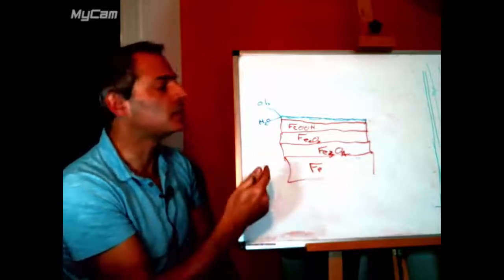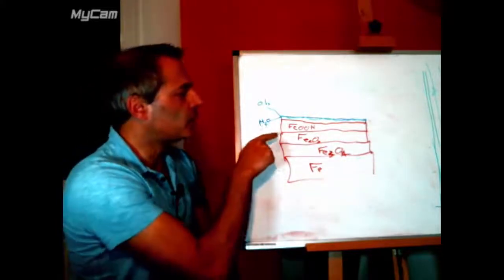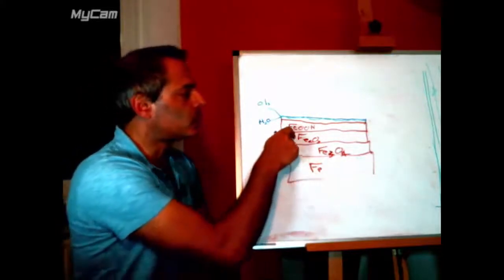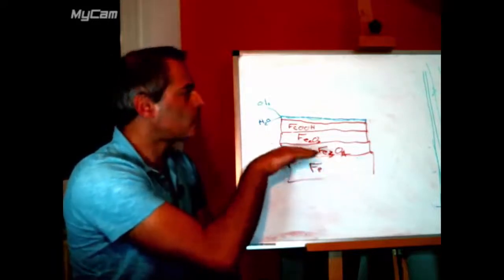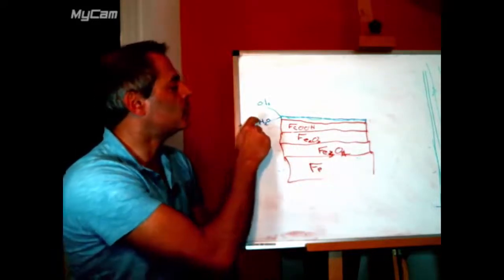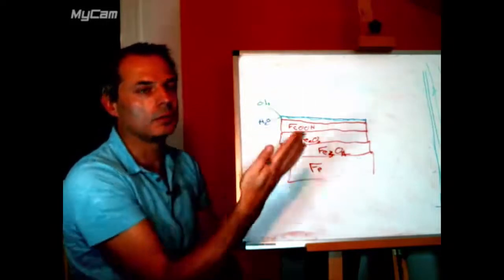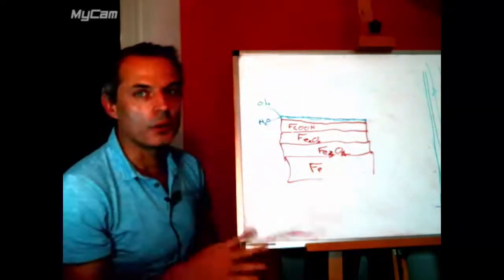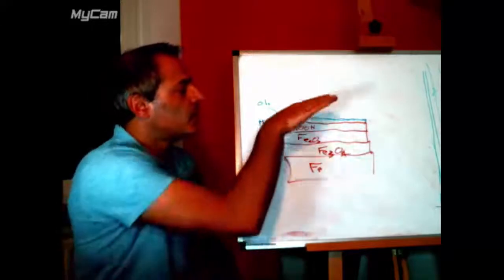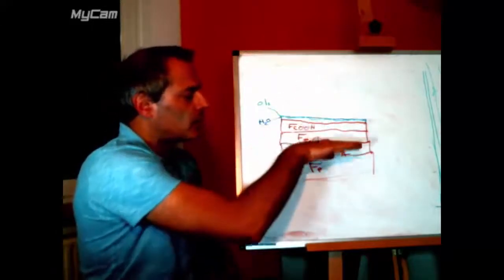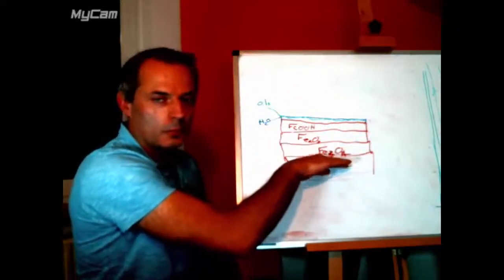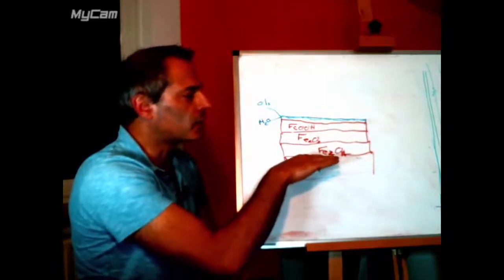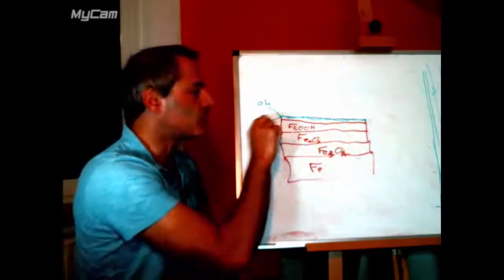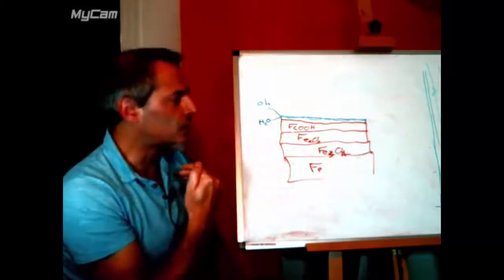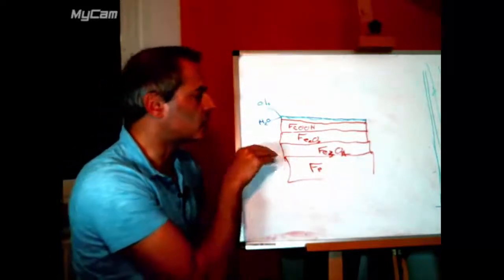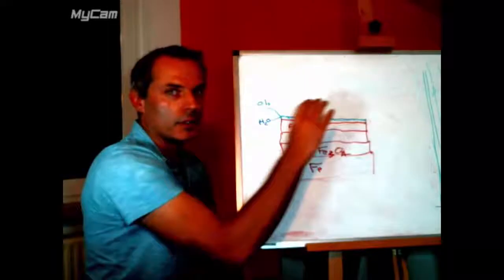So in that case, the zinc is more oxidizing than iron. So it will steal all of the oxygen off the iron, and it is hot. So it will boil all of this water off and probably the oils, although the carbon might well be trapped. And then we will get a zinc to iron, probably a zinc to iron connection, although there might be zinc oxide trapped in between, as long as we sacrifice some of our zinc as oxide to strip off this.